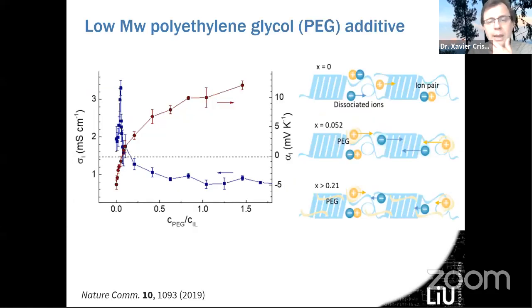But what we discovered is that when we start to add yet another material, a low molecular weight polyethylene glycol—which in low molecular form can be liquid—you just add on top of this material the polyethylene glycol, which is liquid because it's a very short polymer chain, and it completely penetrates the material. And what is happening is very interesting: the thermoelectric properties are completely changing.